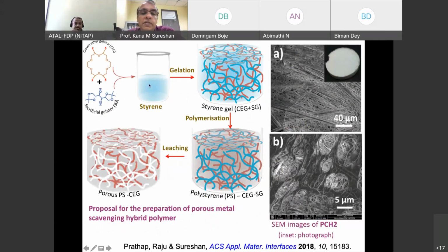Now our idea is here. We take styrene. Styrene is a gelling solvent for this particular crown ether gelator. And this is the other gelator which we have made previously, the mannitol gelator. We take both the gelators using styrene as a solvent. Both will form their own fibers, because this one uses CHO hydrogen bonding for self-assembly and this one uses OHO hydrogen bonding. So they self-sort and form a self-assembly here and form a gel of this styrene. I have shown them in different colors.